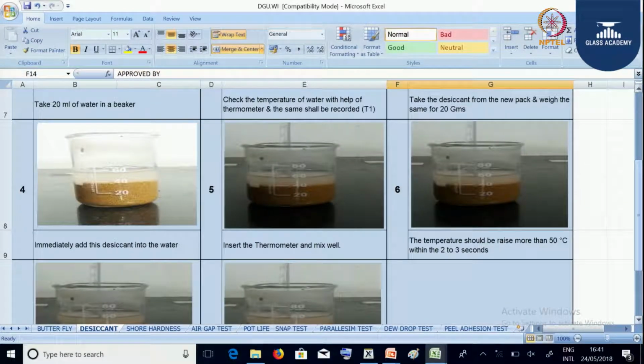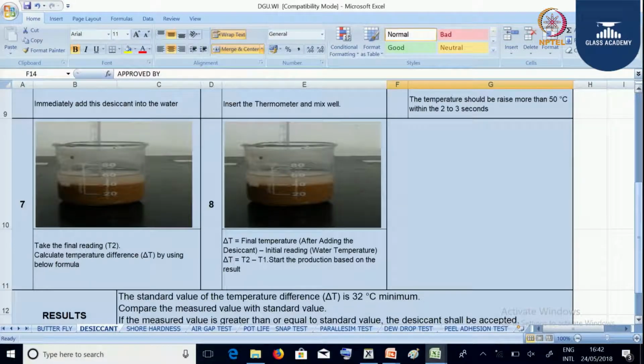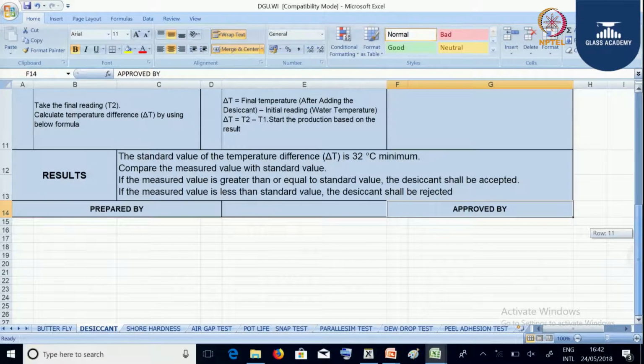Within a fraction of seconds, the temperature will rise. Then we calculate the temperature difference, that is, after adding the desiccant, the new temperature minus the initial water temperature gives the desiccant temperature, and it should be minimum 32 degrees centigrade. The standard value for temperature difference is 32 degrees centigrade minimum.